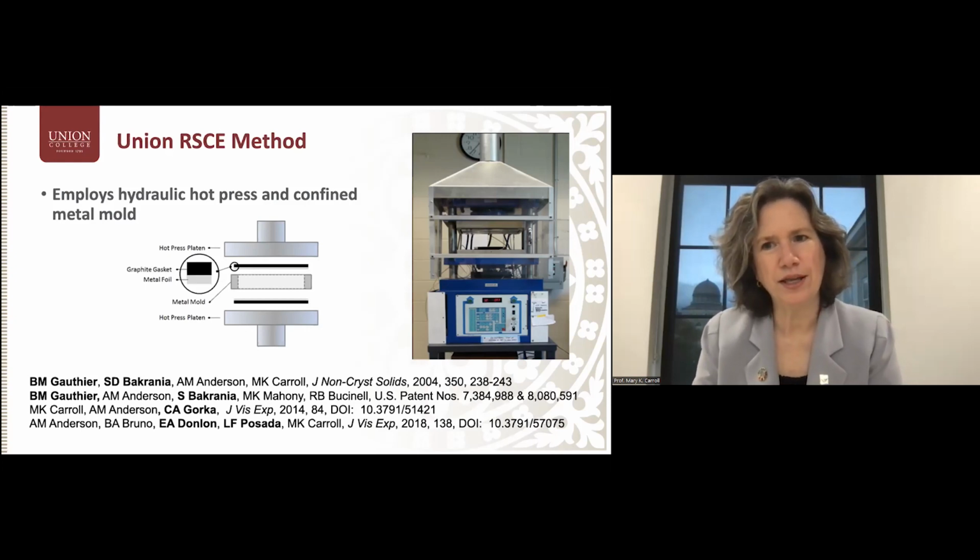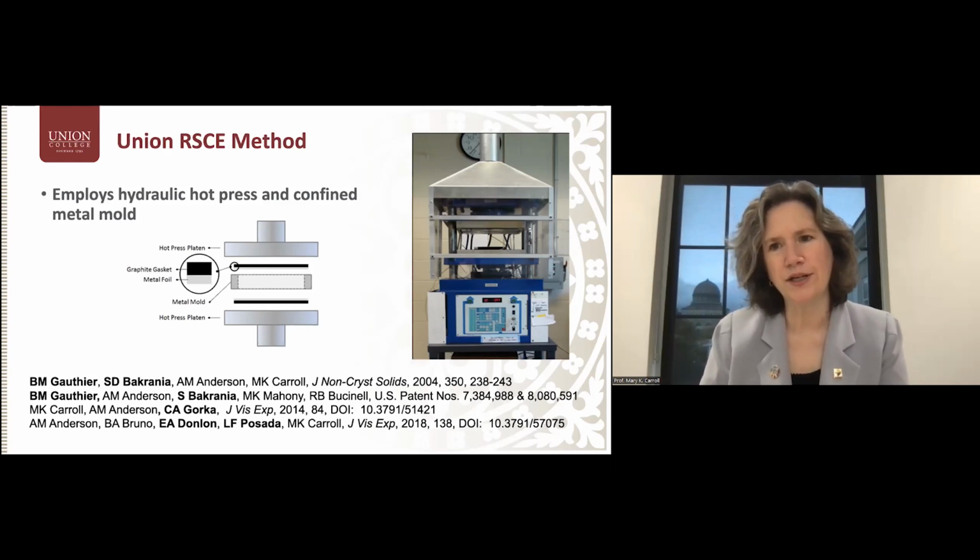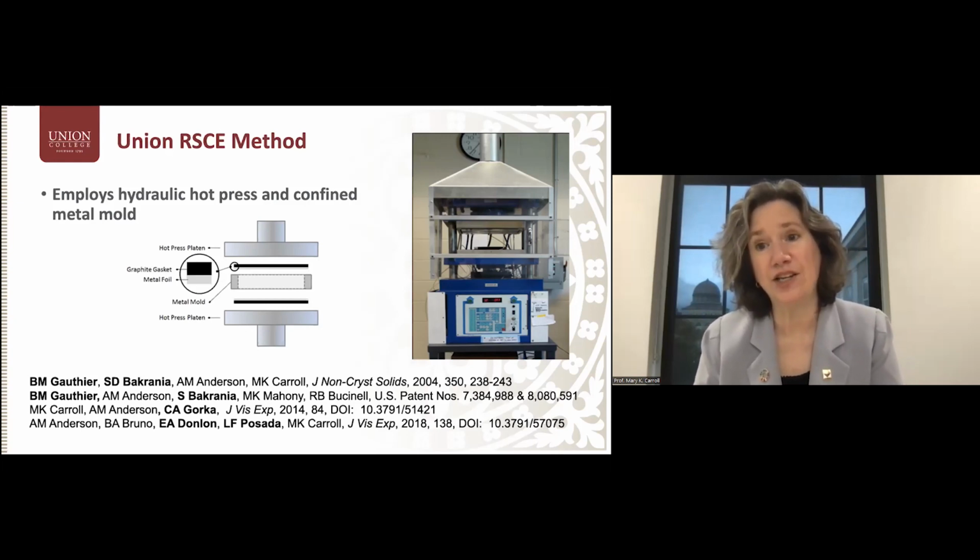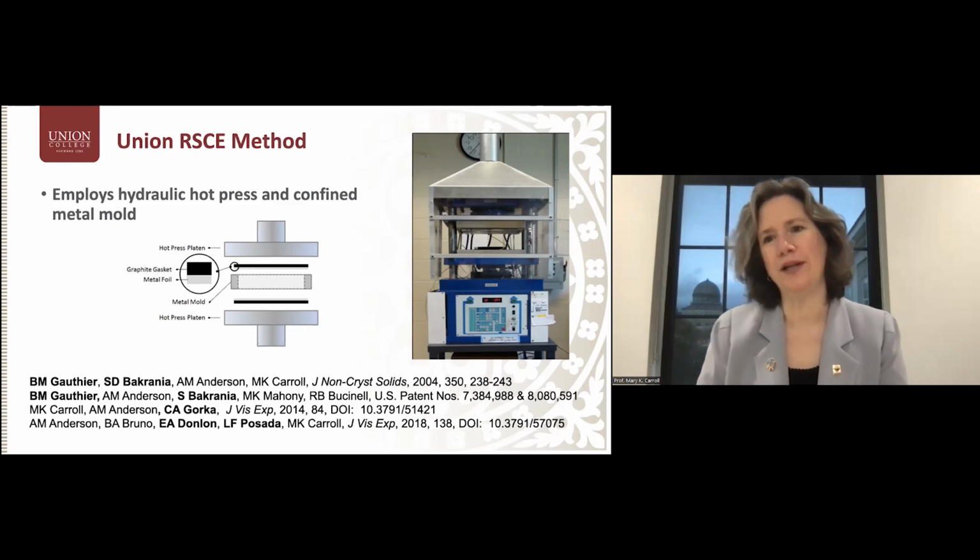So we have, in conjunction with the group at Perugia, been doing a long-term study with accelerated aging, exposure to simulated sunlight and humidity, equivalent to aging. We published a paper on the methods we were using, and we published sort of a midpoint paper when accelerated aging was 12 years.